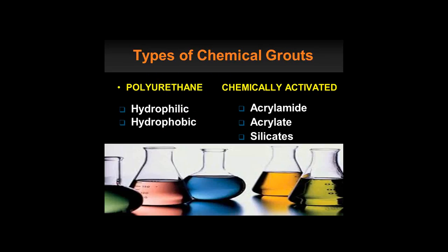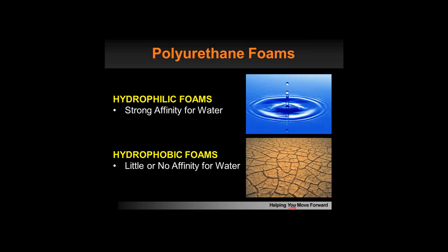Moving on to the types of chemical grouts, two predominant families that are used throughout the industry are polyurethane and chemically activated. Within the polyurethane family, we have the hydrophilic foams and the hydrophobic foams. The hydrophilic foams have a strong affinity for water. They like to be in a water environment. Whereas the hydrophobic foams have little or no affinity to water. They can withstand the wet-dry cycles that may occur on projects.